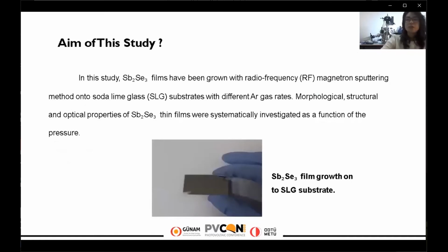In this study, antimony selenide films have been grown with the radio frequency RF magnetron sputtering method onto soda lime glass substrate with different argon gas rates. With different argon gas rates, morphological, structural, and optical properties of antimony selenide thin films were systematically investigated as a function of the pressure.